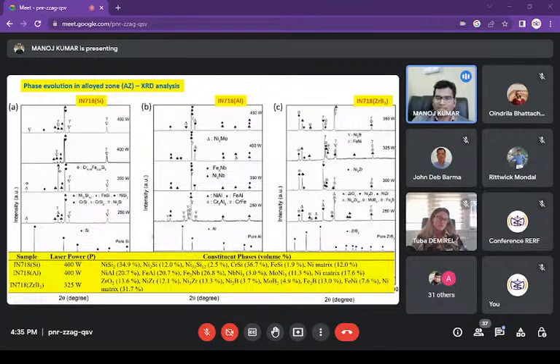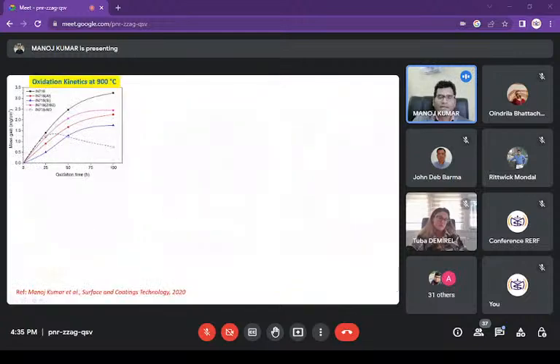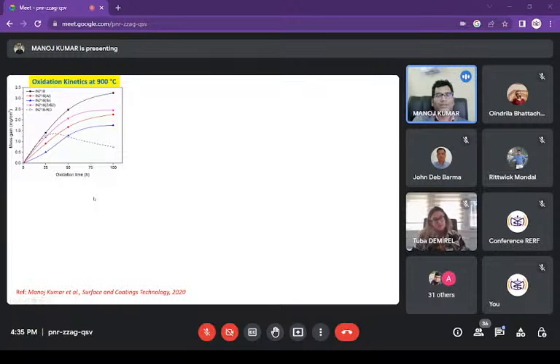So we published this work in Surface and Coatings Technology in 2020, and then we also tried to understand how it is useful for protecting against oxidation during operation. So we subjected the samples to a high temperature of 900 degrees Celsius to understand how the oxidation takes place. We realized that silicon offers the best oxidation resistance. That means it forms the least amount of oxides, so this provides protection from high temperature oxidation.